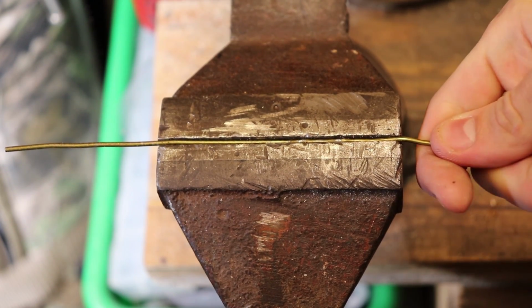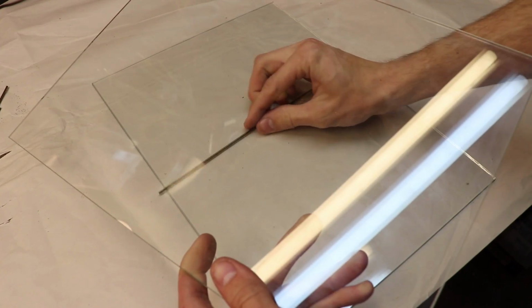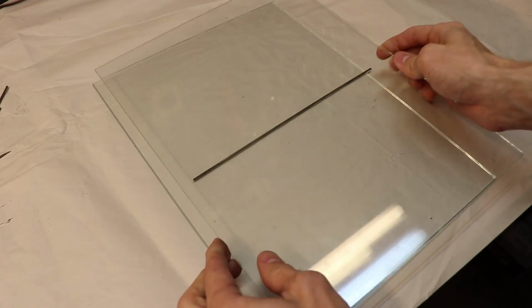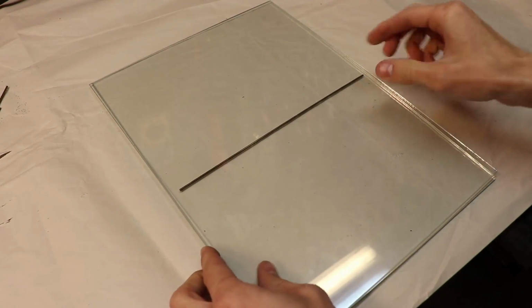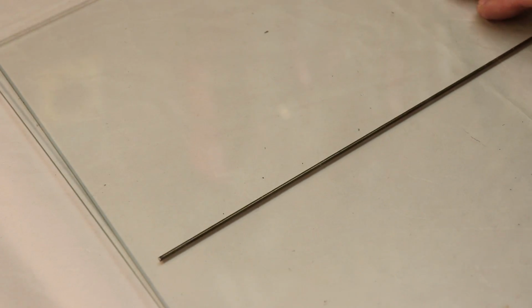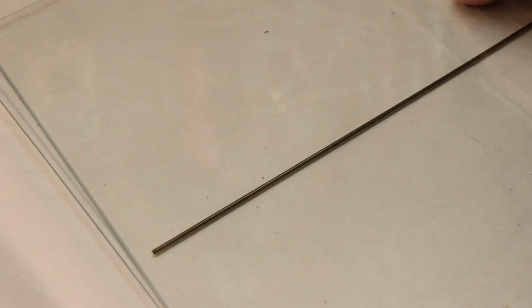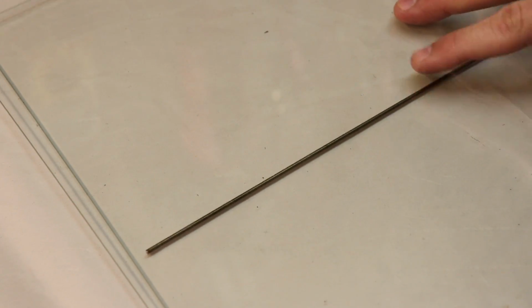To straighten out the segments more, I used my bench vise, and that worked great, but it wasn't enough. I decided a practical test to check if the rods were truly straight is to try rolling them in between two panes of glass. A fairly straight rod will want to roll in between the glass, but a rod that isn't straight will drag itself in between the glass.